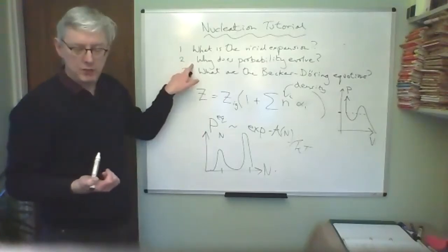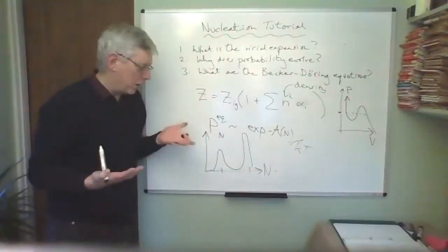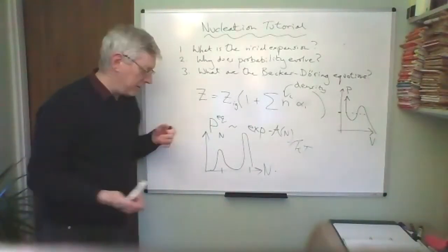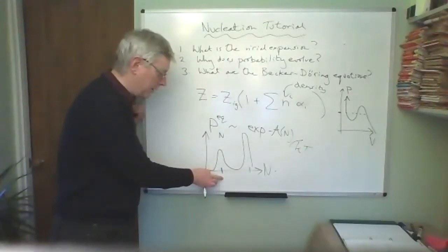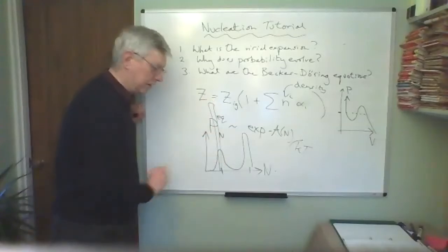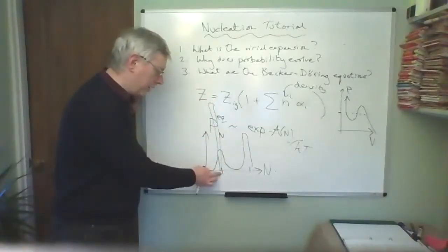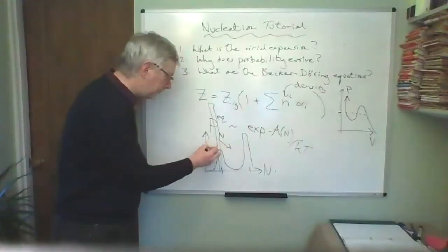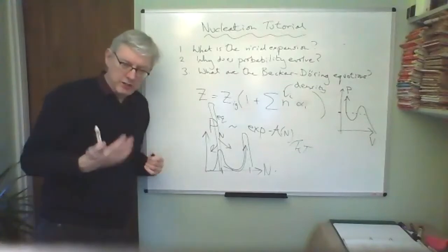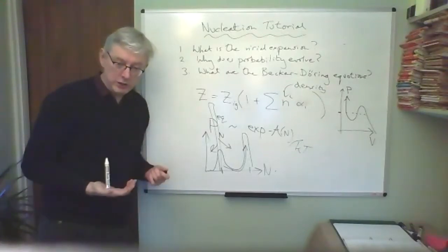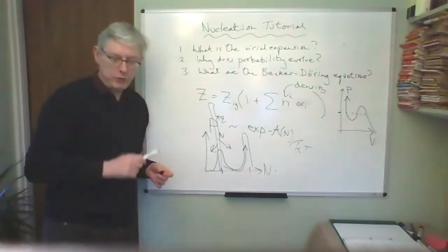In order for there to be a phase change, these probabilities are not appropriate. We have to evolve from an initial probability, for example, of being precisely at this number here, with a density that looks like a delta function, or maybe a Kronecker delta, at this value, but it evolves with time. It spreads and it develops. Time evolution of the probabilities is necessary because we're looking at a non-equilibrium process. We're looking at nucleation. So that was the answer.